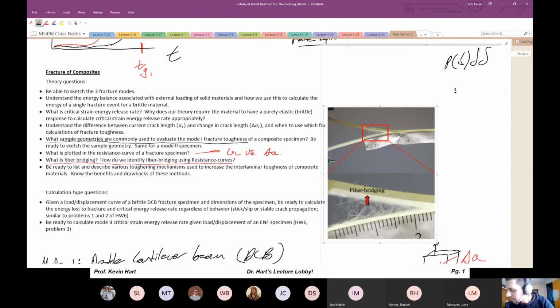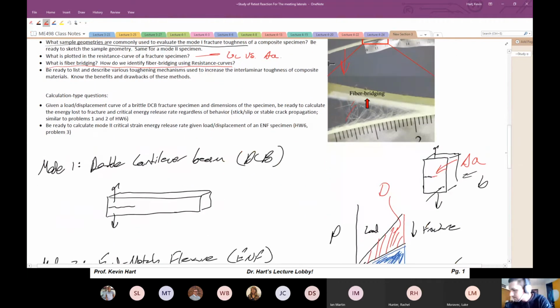All right, here's fiber bridging. You're pulling this guy open, pulling this guy open, and there's all these hairs occurring inside of the crack plane. Those hairs are acting to toughen the interface between the individual layers. When you first start the testing, those hairs are not there because there's a piece of Kapton or Teflon inserted between the layers that stopped that fiber bridging originally.